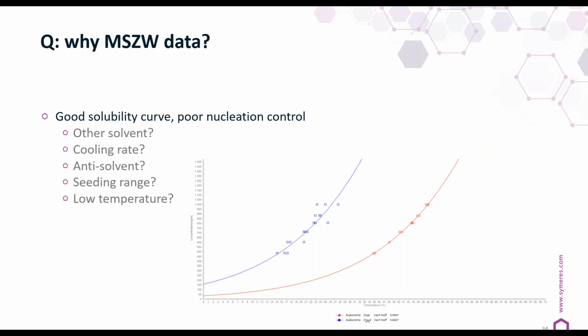Finally, when you have the question on why you should look at your metastable zone width, so why you should look at your solubility curve and your nucleation curve? It's quickly measured, that's one. It's kind of an automated way. You prepare your sample and it's being measured. So it's easy to do. It gives you, in this case, a good solubility curve, but actually it already shows a poor nucleation control.